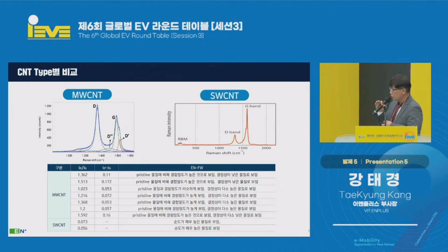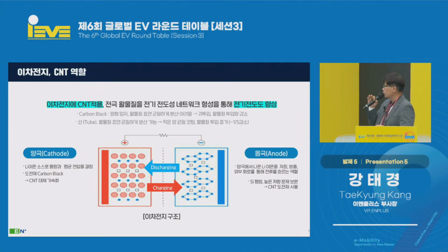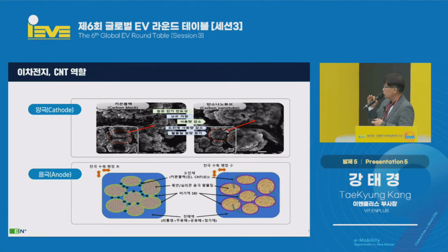And when you develop a full cell with that, the median number is 1.023, and up to that range, the performance is fairly good. But if you're looking for even better performance, then the ID ratio should be 0.053, and with that, the purity would be the highest, and the performance would be the best. And I will skip this because you all know this.